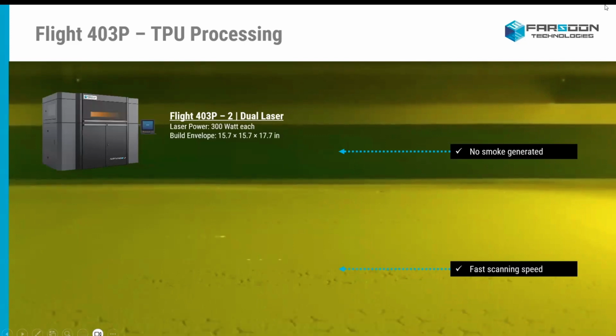The first thing that we can see is that there is no smoke generation while using the fiber lasers. This keeps the laser window clean, which allows us to complete full Z-height builds with little to no operator interaction. The way that the TPU material absorbs the energy from the fiber laser also allows us to utilize the max scan speeds of our flight systems to increase productivity and machine turnaround.